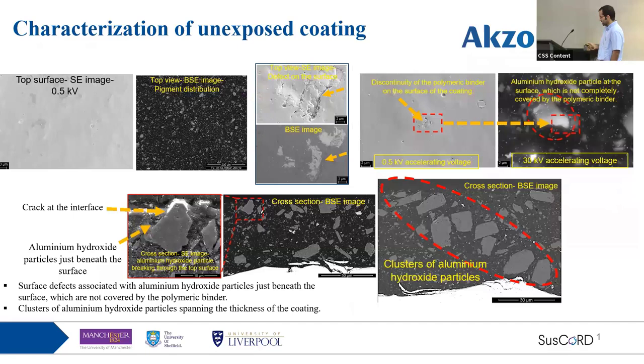So, starting the characterization of the samples with the unexposed panels, I initially used a low accelerating voltage to look at the top surface of the coating. As you can see, the top surface looks smooth, without any apparent defect or significant change in the topography. When we increase the accelerating voltage of the SEM, we can see the particle distribution within the coating, which appears to be random. I haven't been able to detect, at least from the top surface, any agglomeration.